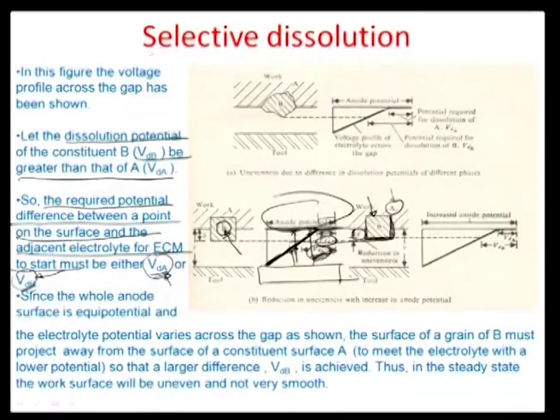So it's an auto roughening effect which is happening in this process because of the differential of potential between the two phases. So it's a main problem in all the ECM processes, particularly with alloys, that there is a roughening action if you cannot choose the alloyed states to have similar dissolution potentials. And life may not be that simple. Two substances may get alloyed not depending on their electrochemical dissolution potentials, okay? So therefore, there is a possibility of a mismatch between the dissolution potentials of two phases, which would create a self roughening effect rather than a self leveling effect. So the ECM process, which is well known for self leveling, may actually be the other way around, okay? So these are some of the typical problems associated with the neat ECM, okay?